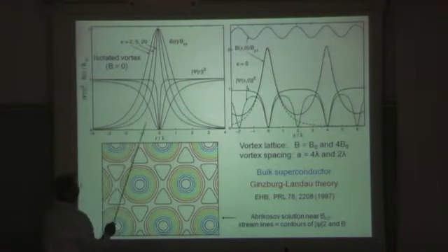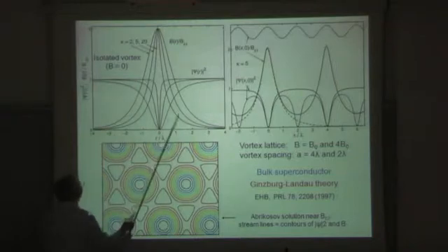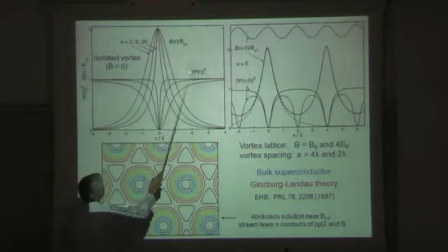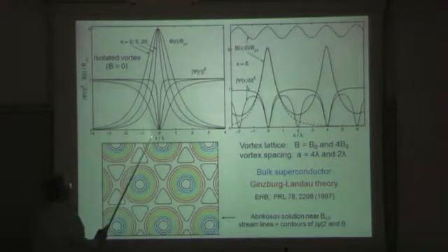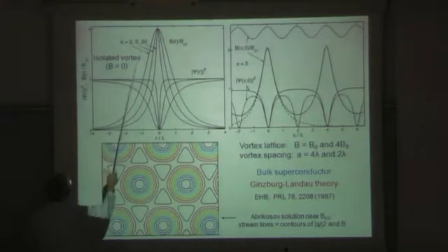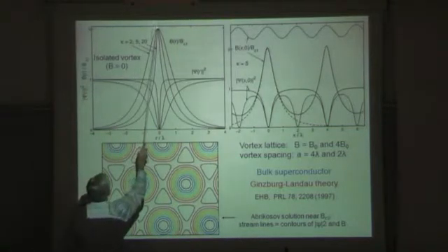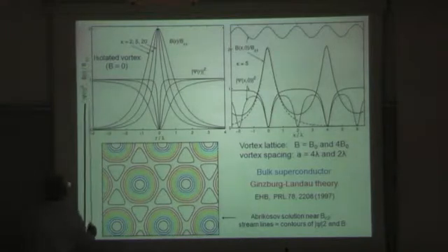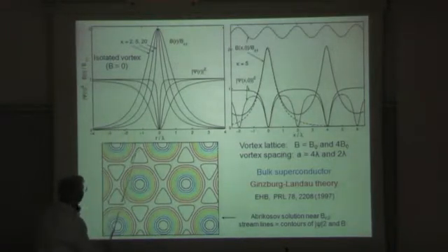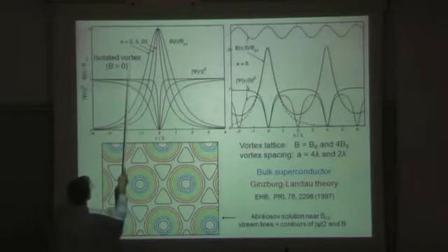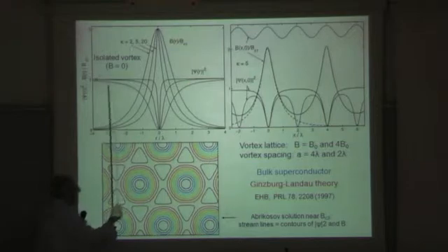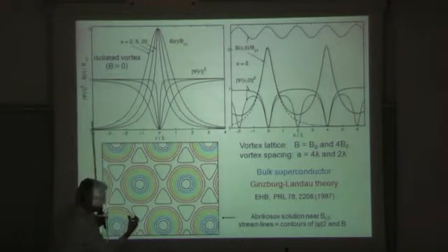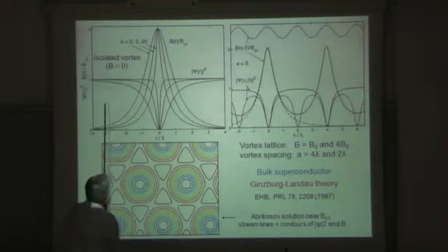I calculated the magnetic fields and the order parameter, psi squared. This is a Ginzburg-Landau function for a single vortex for three different kappa values. An interesting point is that in the center of the vortex, the magnetic field is exactly two times the lower critical field. This follows already from London theory and it applies when kappa is not too small. Kappa equal to two is already a large kappa because the quantity which matters is two kappa squared. So this is a large kappa behavior of a single vortex.